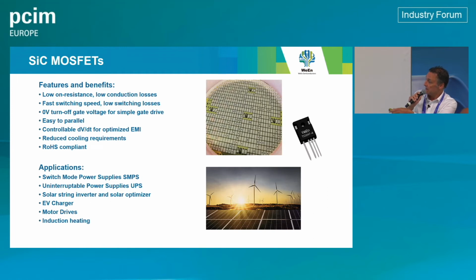So here is the TO247 4-pin package. So this package has an additional lead, which is the Kelvin source. So that's a thin bond wire internally that goes to the control. If you use the 4-pin package, you have better switching performance, lower ringing on the gate voltage, and therefore better EMI, better switching.